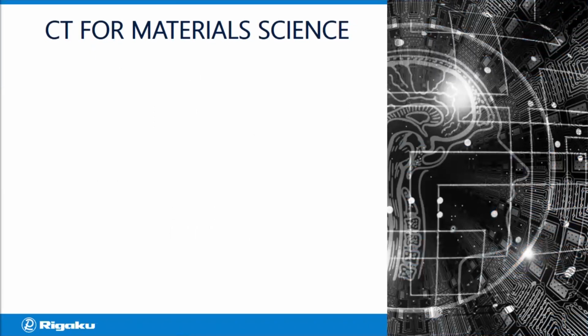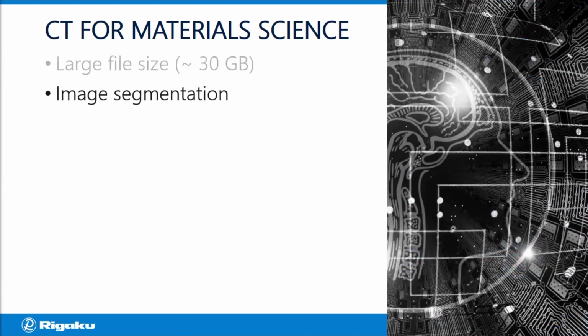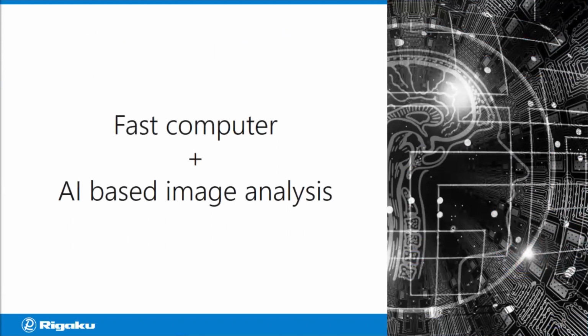For materials research, usually you need a lot higher resolution compared to the medical CT scans, and you always get information in 3D. So your file size tends to be very large, anywhere from a couple of gigabytes to 30 gigabytes. And looking at those images and just making some comments probably would not be good enough for materials science. So you have to do some sort of image segmentation, then ultimately quantitative analysis. And doing those analyses on gigabyte-size files requires a fast computer and sometimes artificial intelligence-based image analysis. And those two things were not available 50 years ago.